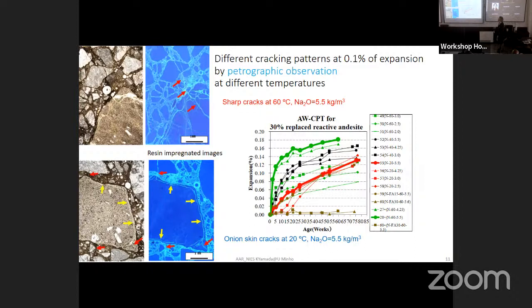And we observe the crack pattern at the same expansion, around 0.1%, but at different temperatures. At 20 degrees, you can see this onion skin cracks. And at higher temperature, cracks pass through aggregate without onion skin cracks. So there's a big difference in cracking pattern.